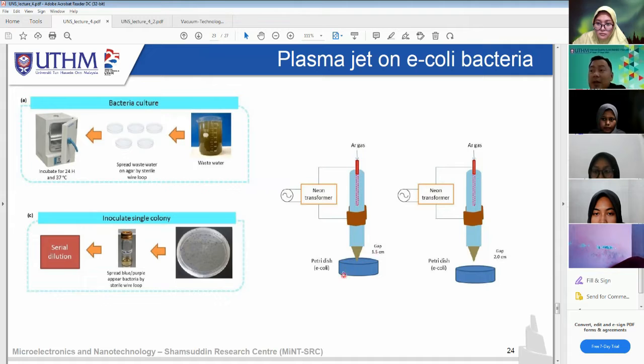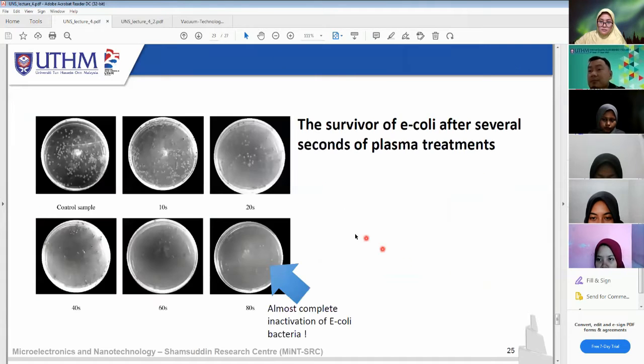We try to observe, for example in this case, we have two gaps, which are 1.5 centimeter and 2.0 centimeter. The one on the left is where we touch, so the plasma will directly contact the water, and then on the right, the plasma didn't contact the water, so we can see the difference.